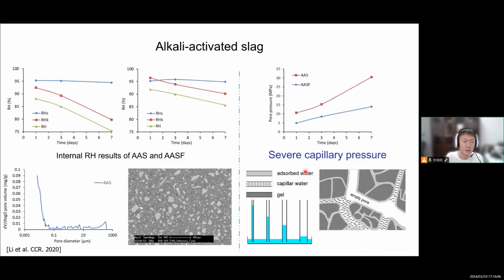And then we explored what is the mechanism of the large shrinkage of AAS or slag and fly ash blended system. The first thing is the same as Portland cement, which means self-desiccation. We measured the internal relative humidity, which actually decreased a lot. Why it decreased so much is because the pore structure is normally denser than Portland cement. You can nearly see no capillary pores here, very dense.